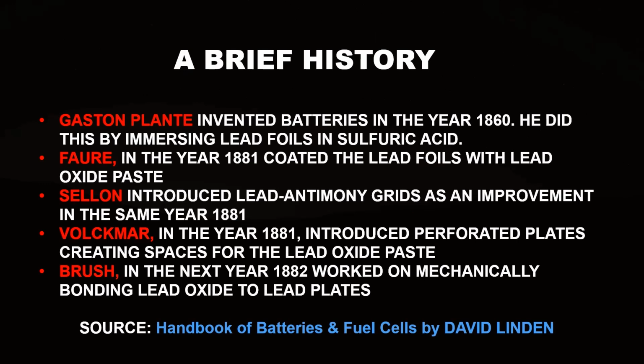I shall now explain the history of lead acid batteries in brief. I need not go into much detail because I have already written it down and it is very clear. Gaston Plante invented the batteries in 1860. He did this by immersing lead foils in sulfuric acid. In 1881, Faure coated these lead foils with lead oxide paste. The lead foils became the conductor and the lead oxide paste became the active material.